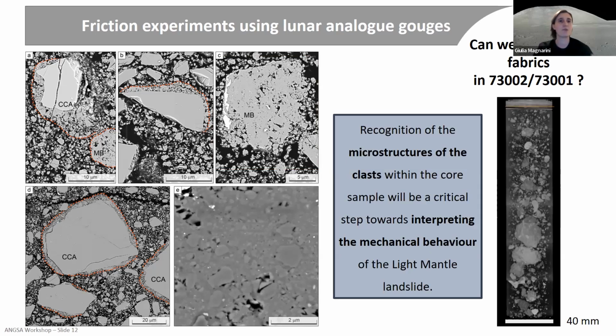Okay, so we generated these microstructures, this clast fabric, when trying to simulate a lunar landslide. And so we thought, what if we can maybe observe similar clast fabric in the core sample 73001 and 002. Obviously, we need to bear in mind different things. First of all, the microstructures that we created with our friction experiment originated close to the slip zone.